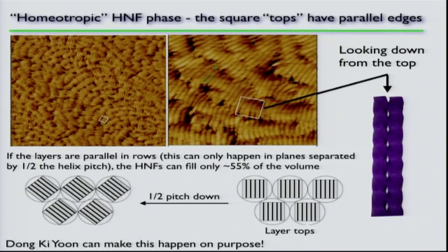that Daniel Kroeke got back in about '97. And so these are the ends of the layers. So you're looking at these things from the top. You're looking down on top of these squares that are inscribed in these circles. Okay, you notice all the layers are parallel. That must mean that there's a plane where all the edges of these squares are parallel. If you go down or up, vertically, then that's no longer true. It looks like that.